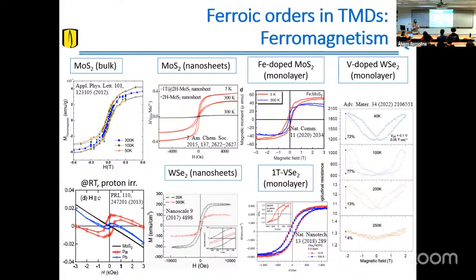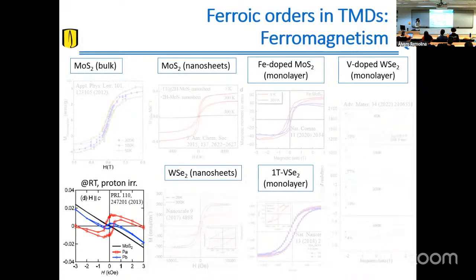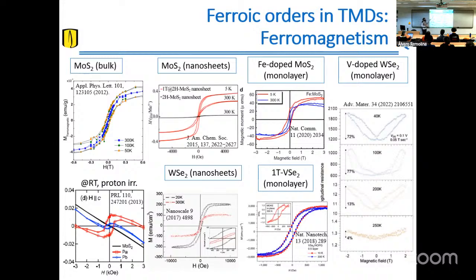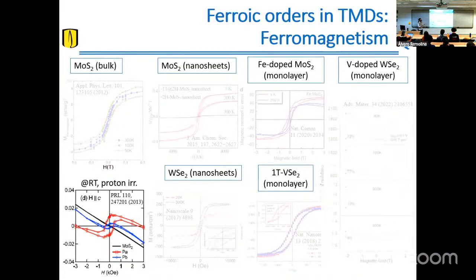As you can see here, there is a lot of research going on around hysteresis loops that have been measured in multiple TMD systems, transition metal dichalcogenides, in which we observe that there are common features in these ferromagnetic loops, focusing on the ferromagnetic side. For example, if we have a sample that is very slightly magnetic, almost paramagnetic, like you see here for molybdenum disulfide, we can actually enhance the magnetism through proton irradiation. So creating defects in the system is beneficial for the ferromagnetic state. That's one key component for the magnetism.